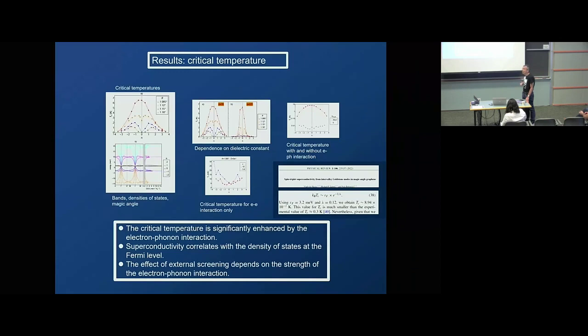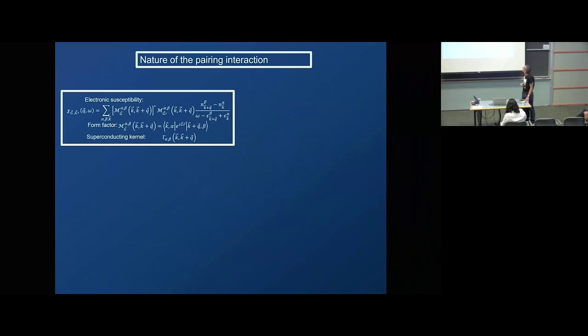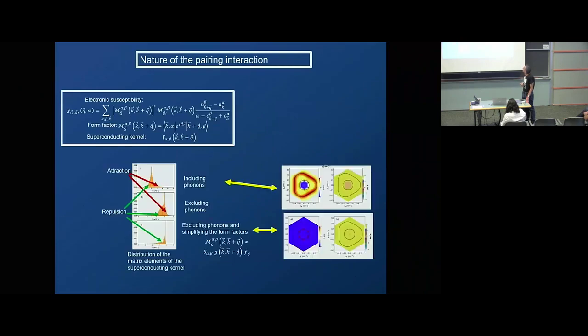There were previous calculations neglecting the phonons, and they are consistent with our results. There, your TC, if you only keep electron-electron interactions, you also have superconductivity, but the TC drops by an order of magnitude. These are more details of how we were calculating things.